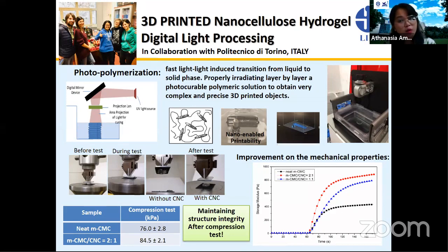We do this in collaboration with the Politecnico di Torino, Italy, and based on photopolymerization, we can input our photocurable polymeric solution. We can also incorporate nanocellulose into the solution, and then by irradiating layer by layer with UV light, we can transform the liquid polymeric solution directly into the solid phase. Once the process finishes in about several minutes, we can obtain a precise and complex 3D printed object of the hydrogel nanocellulose.